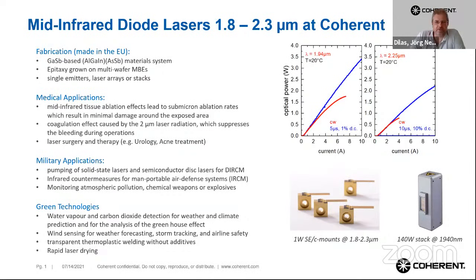So yeah, we work on this range, actually not the full range, but up to 2.3 micron. And I have to confess, we already made more than 3 microns. There are definitely issues in that range for us, coming from high power with cameras or power meters. So all our equipment essentially is not yet fully optimized for above 2.3 micron. But we produce these gallium antimonide based materials here in Europe, and we produce them either as single emitter, as laser bar, or even stacks. For example, on the lower right, you see a 10 bar stack, CW going up to 140 watts per stack. We produced it at 1940, but also at 1908 to pump a holmium crystal, for example.